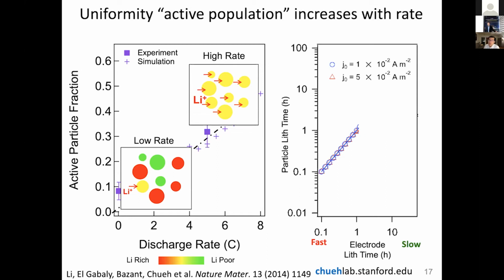This is the plot of the single particle lithiation time versus the electrode lithiation time. So naively, you would expect that the two time scales should match. And when the two time scales match, that means the entirety of your electrode is active. And when you charge and discharge lithium iron phosphate very quickly, on the left of the plot, that's what you see. 1 hour lithiation time for a particle corresponds to 1 hour lithiation time for the electrode, so you have complete utilization. But as you slow down, as you go to the right of the plot, you actually plateau.